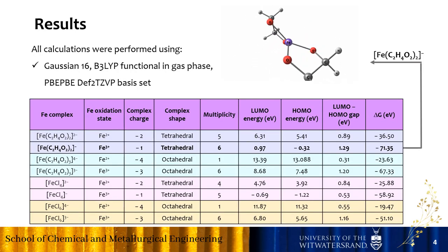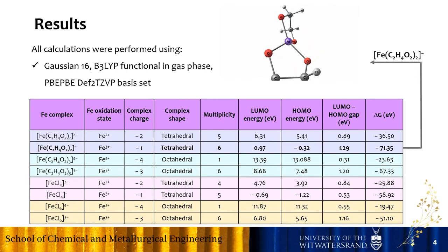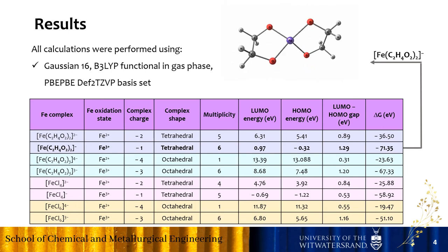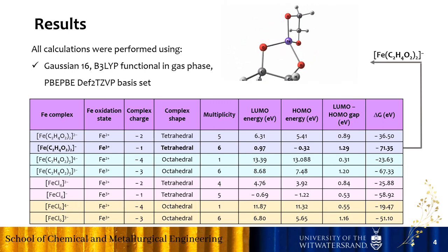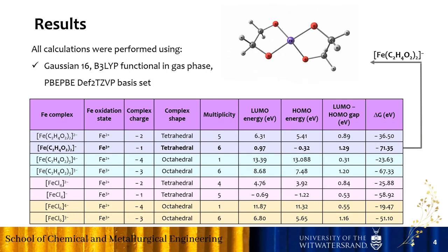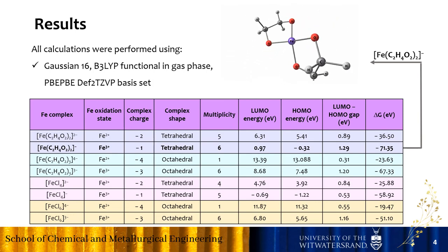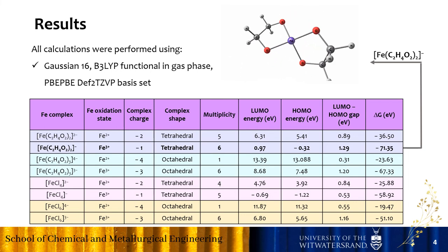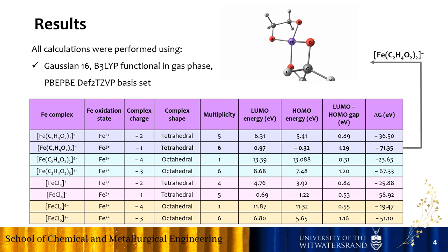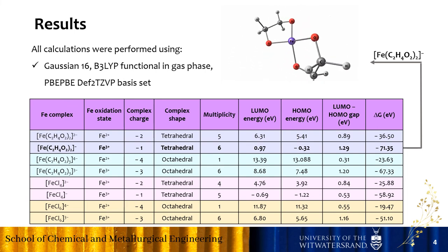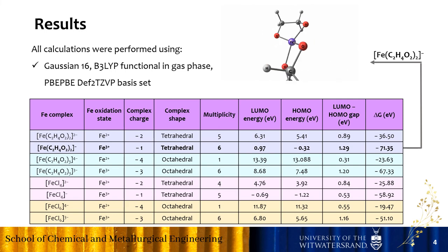After calculating the HOMO-LUMO gap for these complexes and the Gibbs free energy, it was revealed that all eight complexes have negative Gibbs free energy. By comparing these complexes more precisely, it was shown that the combination of Fe³⁺ with two ethylene glycol O-donor ligands has the largest HOMO-LUMO gap, making the complex more stable, and the most negative Gibbs free energy of −71.35, making it the most likely complex to form. All calculations were performed using Gaussian 16 with the B3LYP functional in the gas phase.